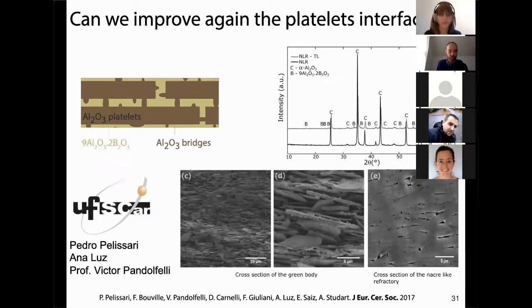So one of their students, Pedro, came to the lab and he developed the same procedure, but again, we changed only the interface composition. And this interface composition should be stronger for one reason, because it's also crystalline. It should be glassy when you heat it up, but at some point it will react with the alumina and form a crystalline phase, which in theory should be stronger than the glassy phase we had before. So again, we try to increase the interfacial strength and see if the mechanical properties increase.